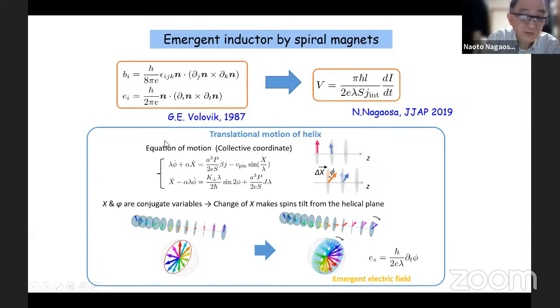And actually this is a typical spin transfer torque mechanism of spintronics, but usually people are interested in the DC translational motion. But once you consider this AC response of this helix structure, then you have a voltage drop which is proportional to the derivative of the current, and the coefficient is nothing but the inductance, capital L. And this lambda is the wavelength of the spiral. And J int is some constant related to the spin anisotropy out of the plane. And S is the spin magnitude. And L is the length of the sample.